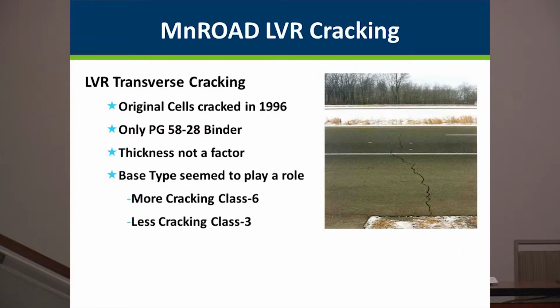thickness didn't matter when it came to thermal cracking. It's just the environment. In our low volume road, we had the same type of thing where we had the same asphalt on the whole thing, but thickness wasn't a factor, and there was sort of an indication of base type. They call it subgrade drag, but asphalt drag when it gets cold, that the coarser types of bases tended to crack more than the finer types of bases.